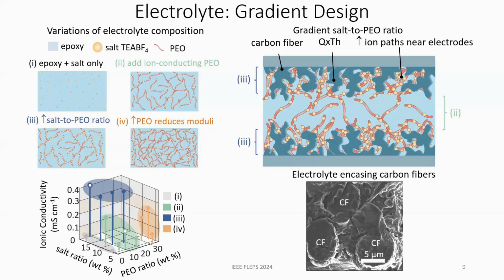Our gradient electrolyte uses regions 2 and 3. So region 3 is near the electrodes. It has our high salt ratio and the medium PEO ratio. So the higher electrolyte salts here help boost the redox performance and keep the channels active. And then the middle region has a higher epoxy ratio to reinforce the device and any external load that would be placed on it. And then you can see here is the electrolyte filling in around the carbon fibers.